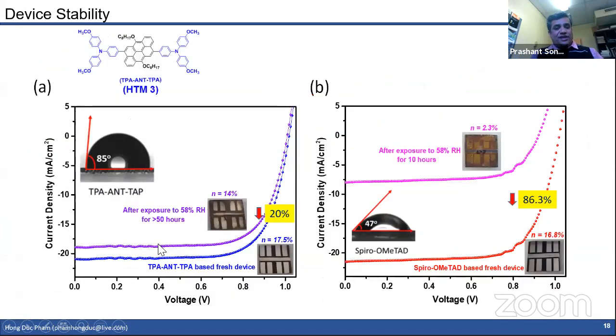And looking again at the fresh device versus the aged devices for 10 hours, you can see that in the case of our newly synthesized HTM material, there is only 20% loss, from 17.5% to 14% efficiency, at a relative humidity of 58%. Whereas in the case of Spiro, which is a commercial, very expensive material with a contact angle of 47, compared to our contact angle of 85, they see 86% degradation. So this clearly indicates that our newly synthesized HTMs have much better stability, and they can last long.